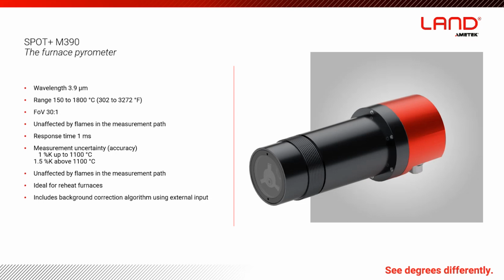Even if you've got some smoke, the longer wavelength will see through smoke much better than our short wavelength pyrometers. There are limits, but by and large, in a furnace atmosphere, the 3.9 micron wavelength works extremely well. It's got a very fast response time, 1 millisecond, which is much faster than any of our older mid-infrared pyrometers, which tended to be up in the 100 to 500 millisecond response time. So if something's happening fast in your process, you can see it.